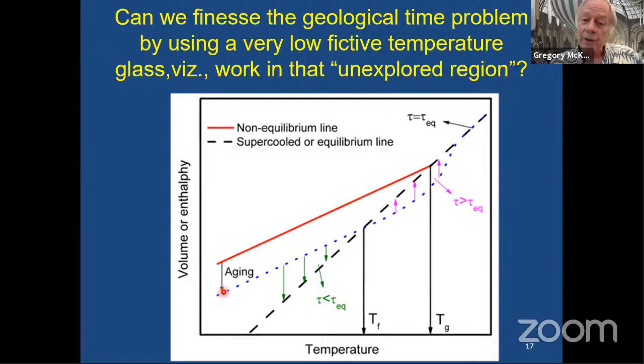And of course, all we really need to know is where its fictive temperature is. And in this case, here's the fictive temperature. And is the distance between the fictive temperature and the glass temperature big enough that I can actually interrogate the behavior over a reasonable window of temperature? Because below the fictive temperature, these are shorter than equilibrium time. So that doesn't test anything for me. I already know that when I'm up here, they're shorter than Vogel-Fulcher. We already know that. The question is, when I'm over here in an upper bound condition, do I see something faster or shorter than the Vogel-Fulcher, or do I see something even longer? And then, of course, as I get above TG, then I'm at the equilibrium time.